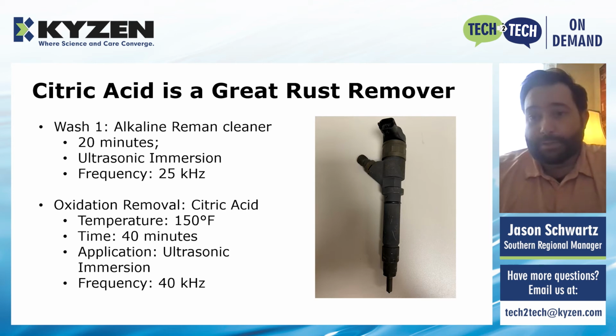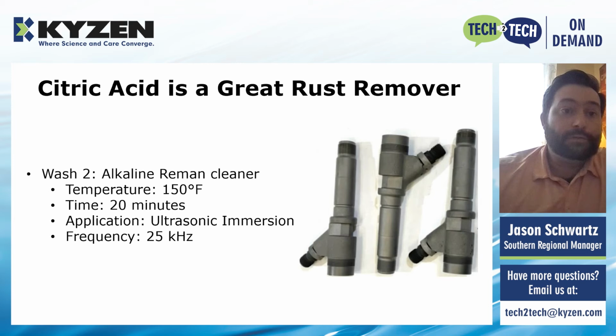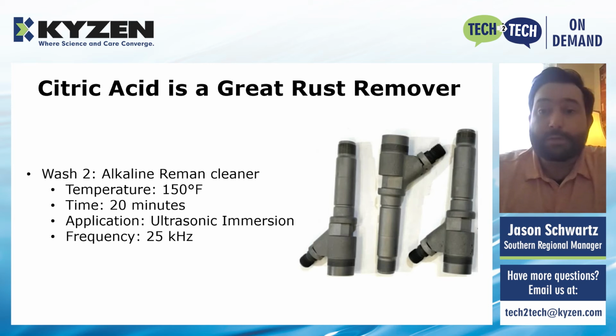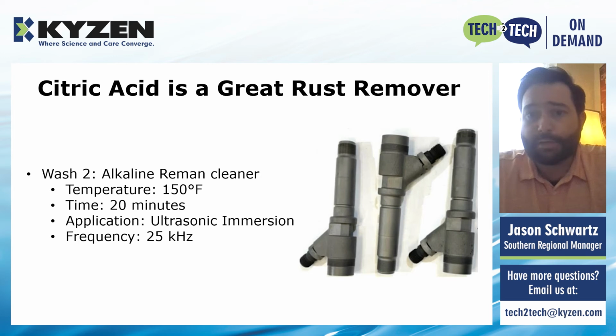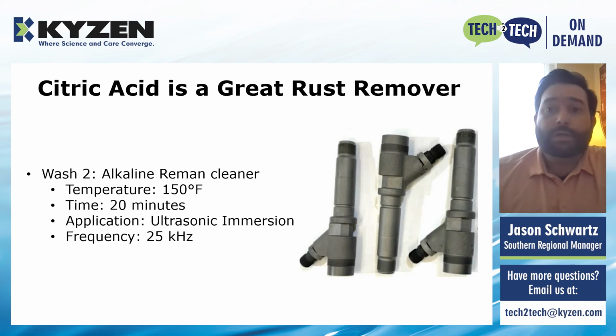However, that is just the citric acid working to coat the part in a black oxide instead of that ferrous iron oxide. So that black oxide, if you go into a second wash stage, can be pretty easily washed off with that same chemical from the first step, just your standard alkaline reman cleaner. And so you've gone from taking a really heavily rusted part and you've given it this nice even finish and taken off all of the rust using just your regular alkaline cleaner for oil and grease and citric acid.